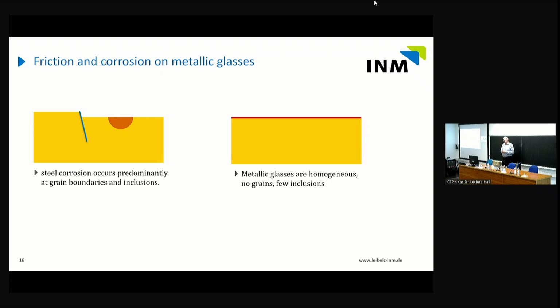So then I said, if that's not possible, let's look for a metal without any dislocations, grain boundaries, or anything. So that's a metallic glass. A metallic glass is theoretically perfect. It's without any structural defects, or if you wish, it consists of structural defects. That depends on your view. So happily, University of Basel is still doing high-quality metallic glass films, and they gave us samples. So, as I said, we have these little volcanoes and that doesn't work, and so we hope that there will be some smiley on electrochemical AFM here.